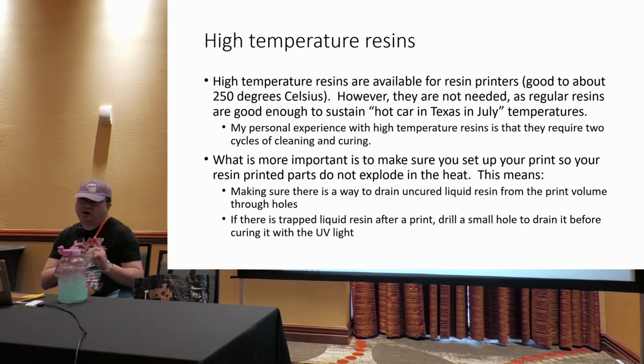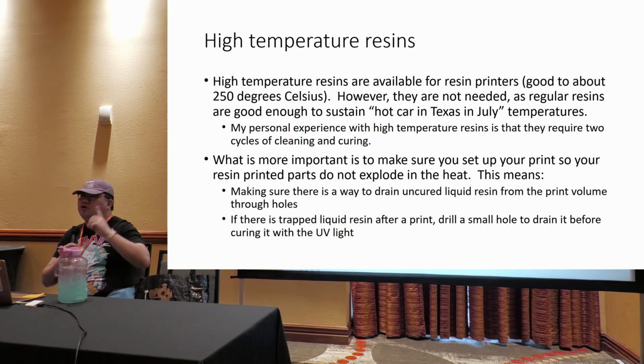The more important thing about resin printing in general, if you want to make a resin print survive a high heat situation, is you must make sure that your parts do not explode under heat. The reason they explode under any sort of heat is because your resin printed part has uncured resin inside the volume. When you do resin printing, you often see instructions saying you must make a drain hole in your slicer software to drain out resin. If you don't drain it out, all of it, you have a problem.